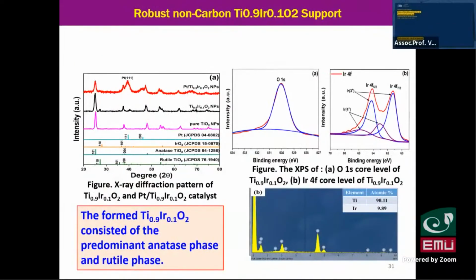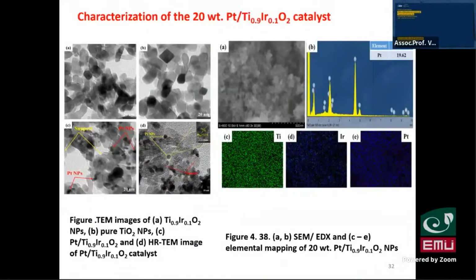This is some results we have done for this topic. We also found the structure, the composition, and also the morphology and electric property of this catalyst. TEM shows our material, titanium iridium oxide, is very uniform.